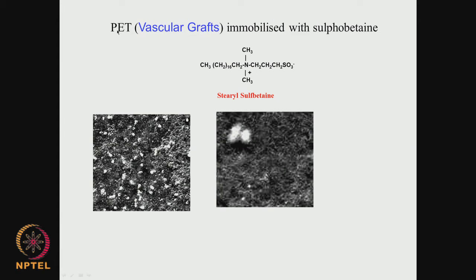Let us look at a few more of these approaches. For example, polyesters — such as polyethylene terephthalate — are widely used in large-diameter vascular grafts. If we immobilize sulfobetaine, which has a zwitterionic type of charge (N+ and negative charge), on these polyesters using zwitterionic material modification, this picture shows the attachment of bacteria on pure polyester versus after modification. We can see there is significant prevention of bacterial attachment, showing this could be one technique for reducing bacterial attachment.